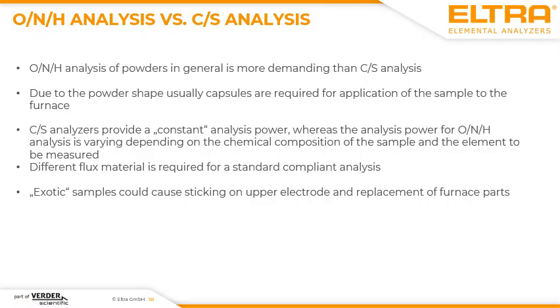The other trouble is when you don't know the exact chemical composition of your powder, it's maybe critical to find the correct, I would say, application power. In a carbon sulfur analyzer, we always have the constant power, just given by the kind of accelerator. In an Elementrac ONH-p2 or other ONH analyzers, the applied power has to be adjusted a little bit differently for every analysis. Depending on the chemical composition, you also have to consider that you maybe need some flux. And it could also happen, and this has to be clarified before starting the analysis, that some samples, for example, stick on the electrode. For example, lithium-based samples could show some very bad effects.